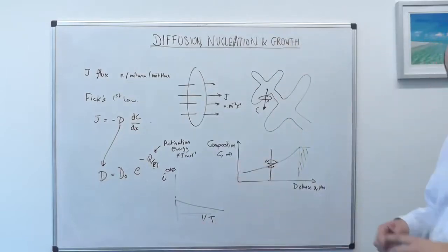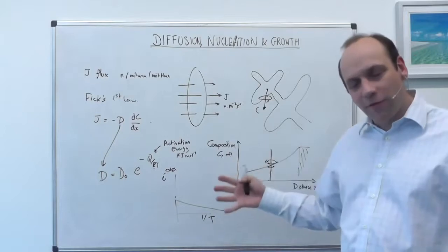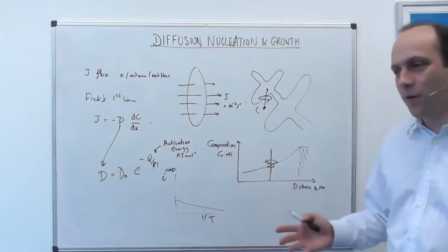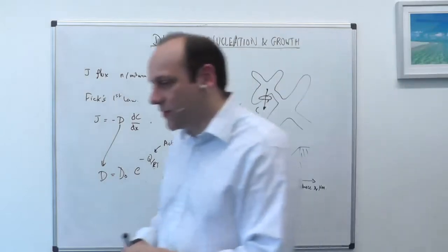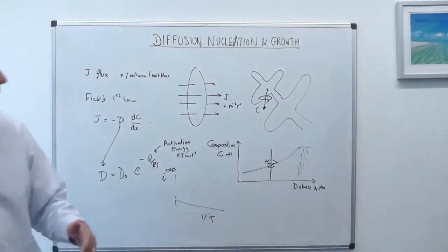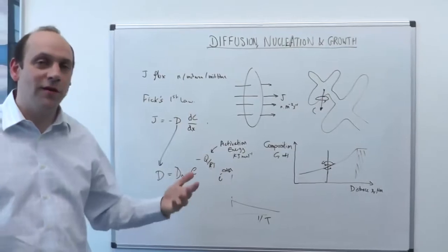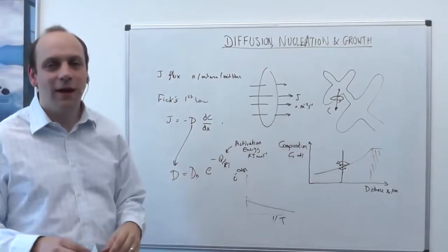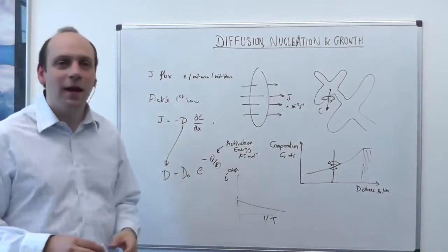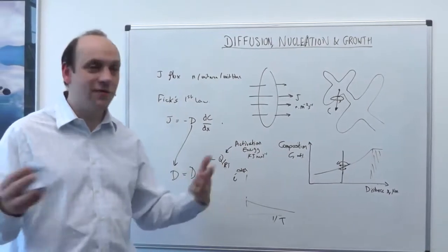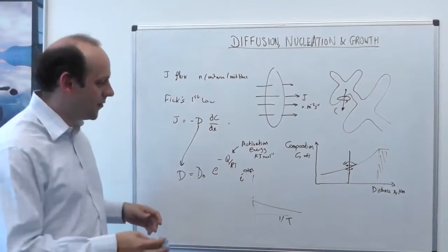So if we homogenize at high temperatures, everything will flatten out quickly, and if we homogenize at low temperatures, it will be very slow. Practically speaking, in a nickel superalloy, there's no real point trying to do a heat treatment to homogenize at low temperatures, at 600-700 degrees. You need to get up to temperatures like 1,000 degrees, and that's for an alloy that melts at 1,300.